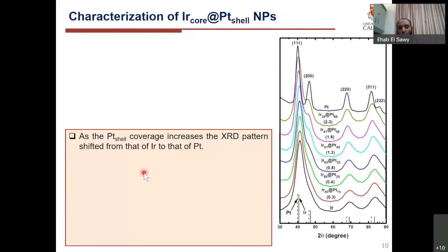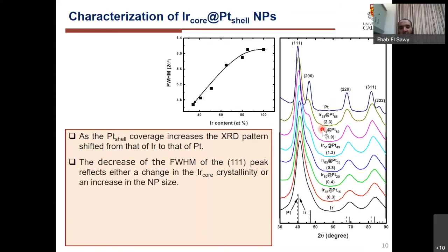Then, to explain whether there is a strain effect during the growth of the platinum shell on the iridium, we did XRD for all the prepared catalysts. As we could see, the iridium XRD gradually changes to that of platinum with increasing coverage from sub-monolayer to about 2 monolayers. It also shows a decrease in the full width at half maximum. This indicates two things: either the iridium core starts to rearrange and become more crystalline so the crystallite size increased, or it only indicates the particle size increase.